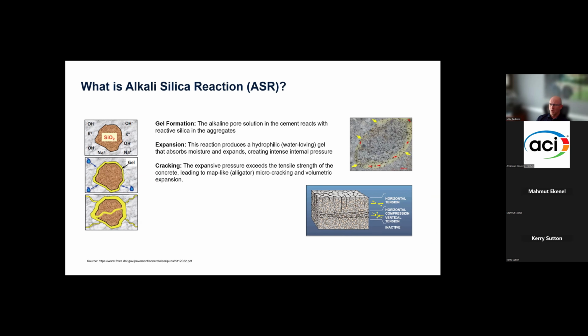How it happens is a gel forms in the cement around the aggregates as a result of these reactive aggregates and the cements having a chemical reaction. That gel, when it comes in contact with moisture, which most concrete does, will begin to expand. When it expands, it puts intense internal pressure on the concrete, which leads to cracking. And not just an occasional crack here or there. It's really like an alligator crack, major cracking, deterioration of the slab or the structure.